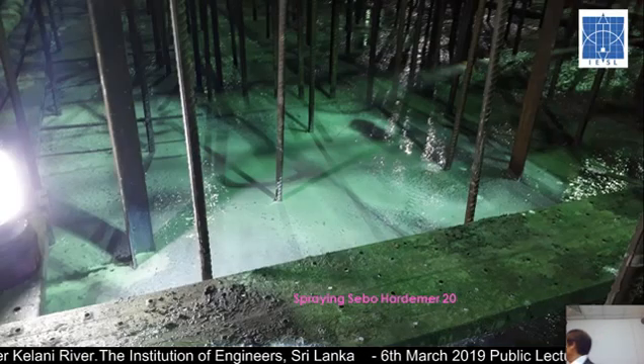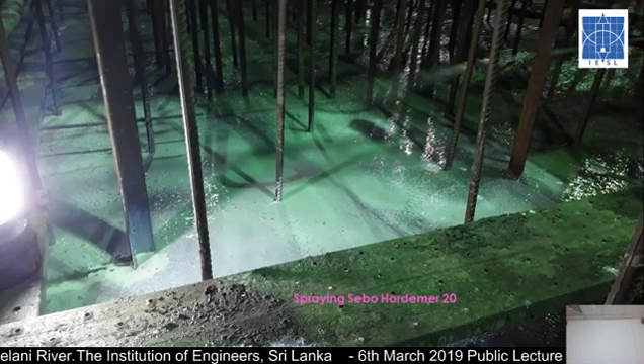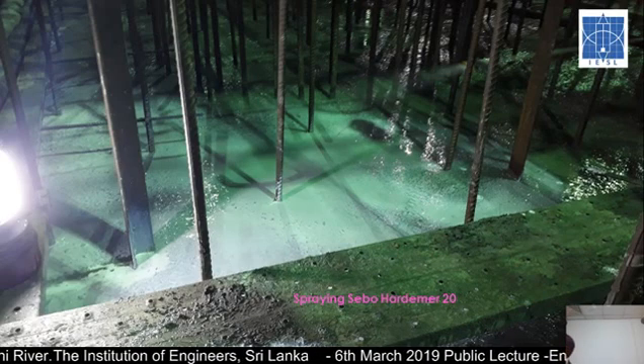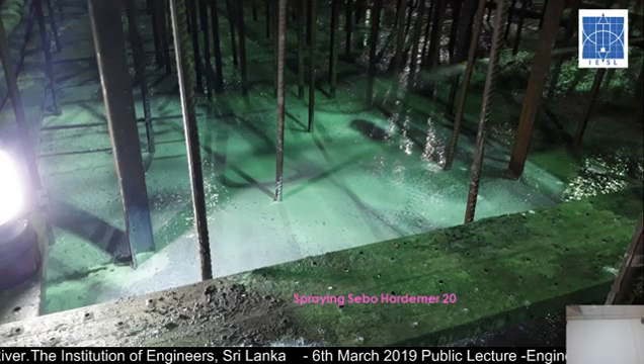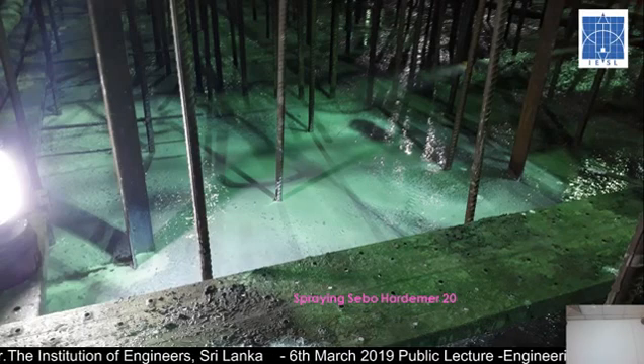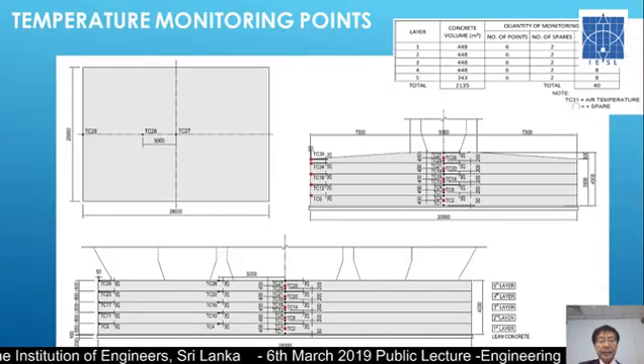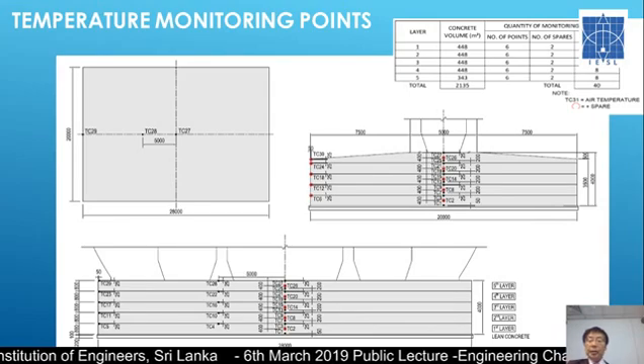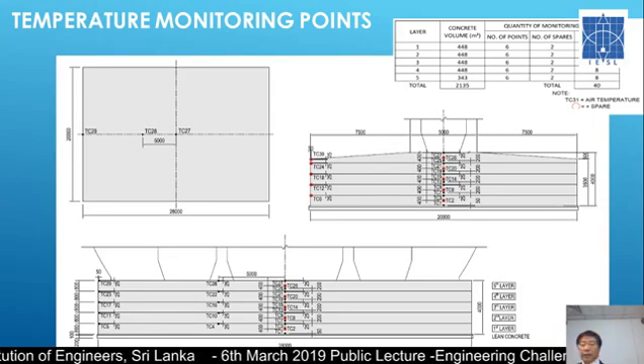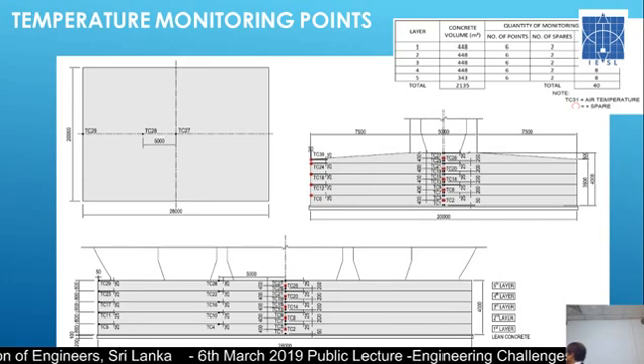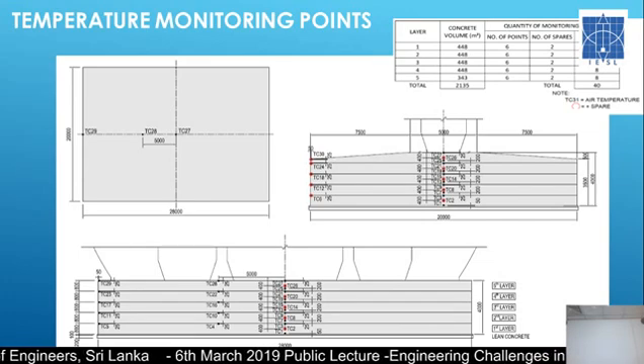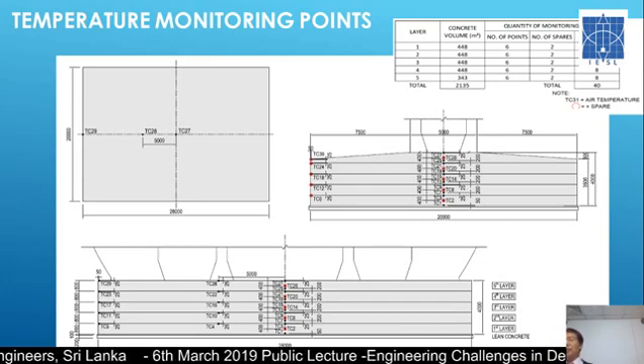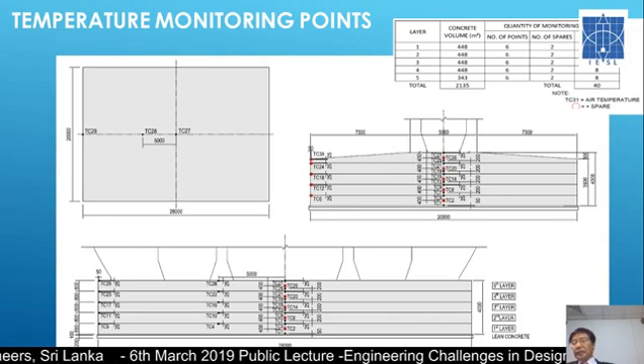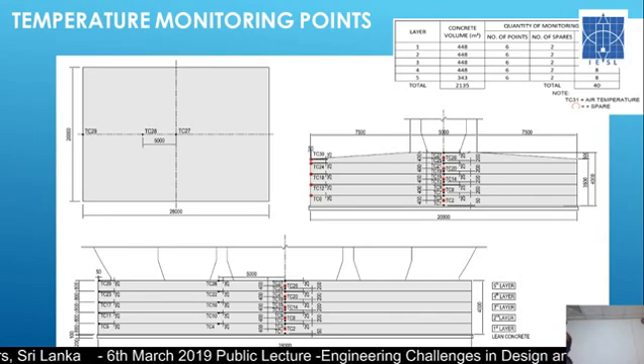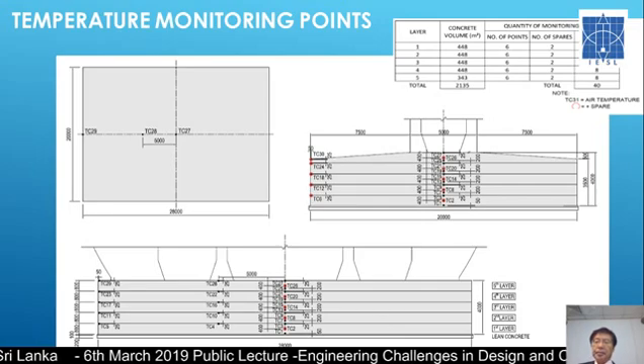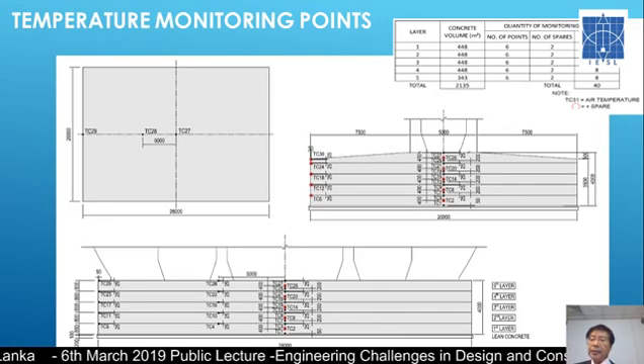This is an actual construction site. This white color is a bonding agent. It's sprayed over the interface between the layers. This is the temperature monitoring point for the actual structure. We have several locations. For each layer, there are six measuring points, at the core and the surface. So the total number of measurements is quite big.